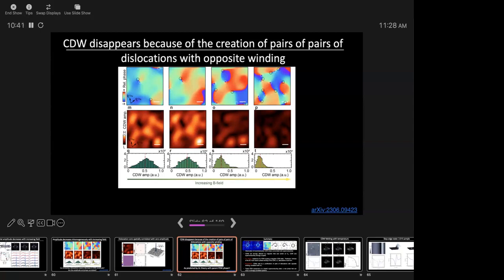Okay, more questions. Well, Frank is next. Yesterday it looked quite convincing that the CDW's temperature is higher than the potential PDW's. But in order to answer the question of what is parent and what is daughter, couldn't you just repeat this experiment at different temperatures and see if at a certain temperature you no longer induce dislocation pairs in the CDW? Yeah, so we have to do that. This is at low temperatures, all below TC. So we're trying to do that. We're trying to do magnetic field dependence at higher temperatures.